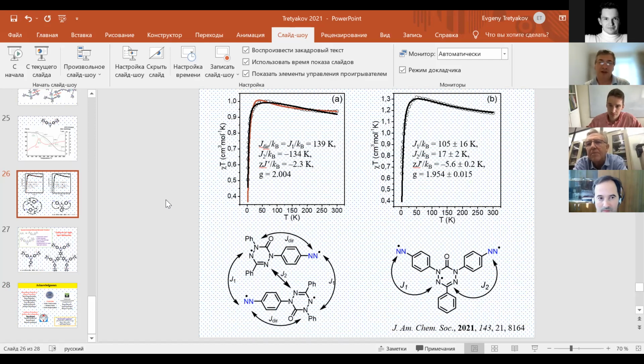Yes. The other question is about sublimation. Some of your samples can be sublimed, but when you sublime the sample, do you obtain crystals? You can control that the film that you form is amorphous or not, or you have no control over the crystallinity of the sample? We observed formation of thin crystals. Yeah, I know, but it's possible also to try to sublimate fast, in such a way that you form a film with a very small size of the crystals. This is interesting also from the point of view of devices. That's why I asked, because one possibility is to sublime to obtain big crystals and study them, but the other possibility is to prepare films as amorphous as possible, with quite small crystallites, in order to make thin films. Yes, indeed. I agree with you.